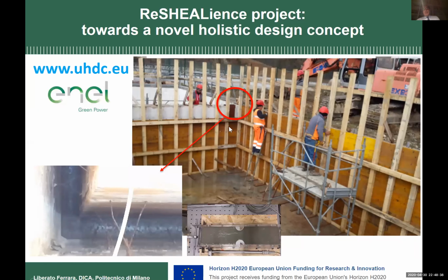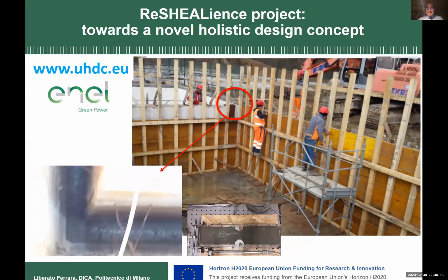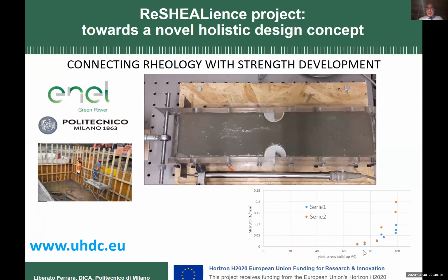Since this material is highly fluid, one of the problems was also designing the formworks for static pressure and understanding how fast the strength developed. This is a tensile test made after half an hour with a specific setup we developed, and we correlated the results to the rheology of the material and to the yield stress buildup.